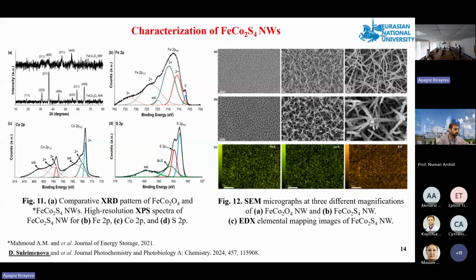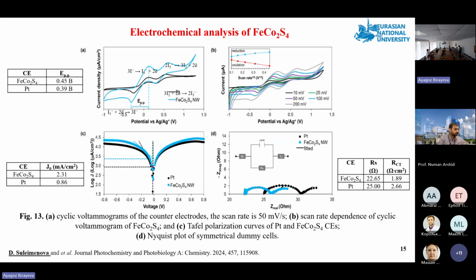For this slide, we can see the characterization of ferrum cobalt 2 S4 nanowires. XRD and XPS analysis confirmed the successful formation of ferrum cobalt 2 S4. SEM shows that ferrum cobalt 2 O4 has a nanowire structure. Average diameter is 92 nanometers. After sulfurization, the ferrum cobalt 2 S4 nanowires increased in diameter to approximately 199 nanometers due to replacement of oxide ions with sulfide ions. EDS confirms uniform distribution of ferrum, cobalt, and sulfur, indicating successful formation of pure ferrum cobalt 2 S4 without impurities.